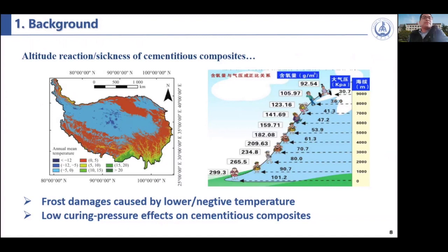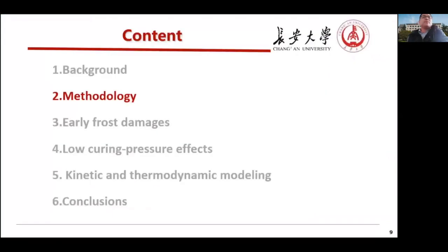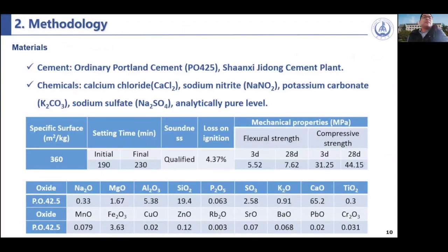Today, we want to introduce two parts. The first part is the frost damages caused by lower or negative temperature. And the second part, we want to introduce some basic results or conclusions we got on the lower air pressure effects on cementitious composites. The material we used is the commercially used ordinary Portland cement produced in Shaanxi province, and the chemicals mixed into the cement are calcium chloride, sodium nitrite, and some other salts. All the cement was measured and can meet the required specifications in China.